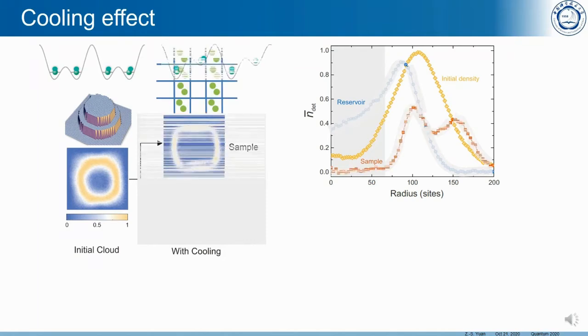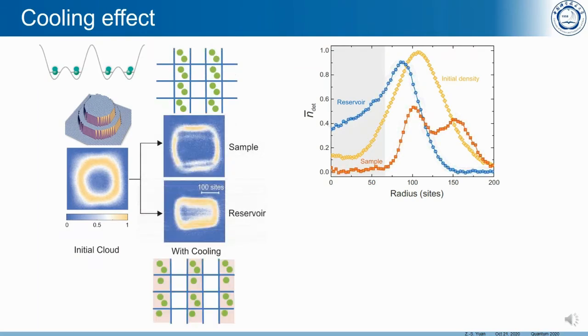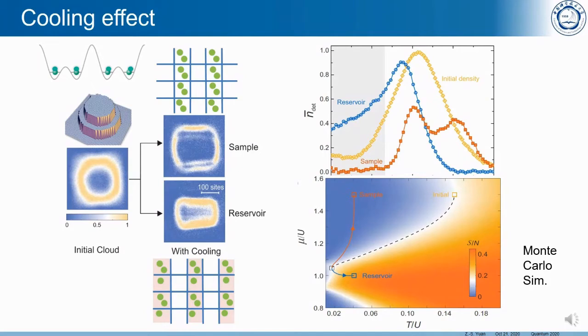Here shows the cooling effect. The left panel shows that during the phase transition, we use the balanced superlattice. Therefore, the entropy distribution is homogeneous along the whole lattice. Comparatively, based on the cooling scheme, we use a tilted superlattice. The samples have a much lower entropy, while the reservoirs have much higher entropy. The measured atomic densities confirm our expectation. If we use Monte Carlo simulation to simulate our experimental process for an initial gas, after the cooling, we have the reservoirs with a higher entropy, while the samples have a much lower entropy.